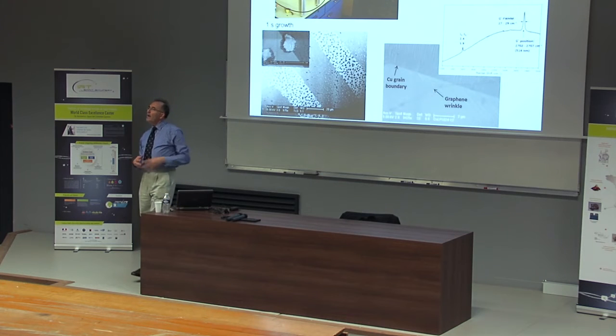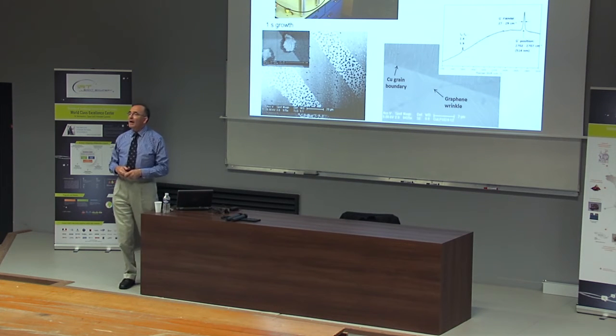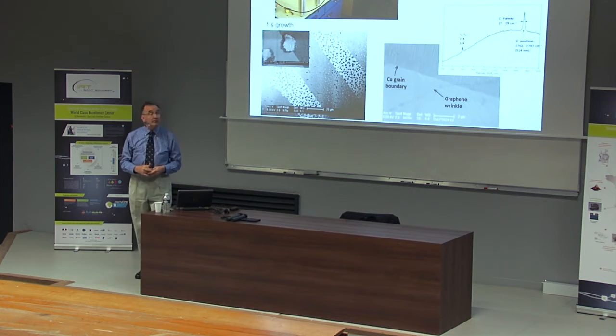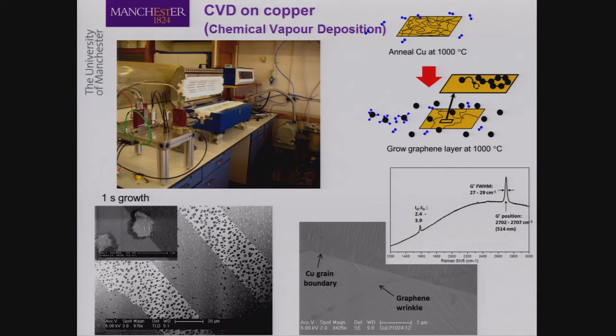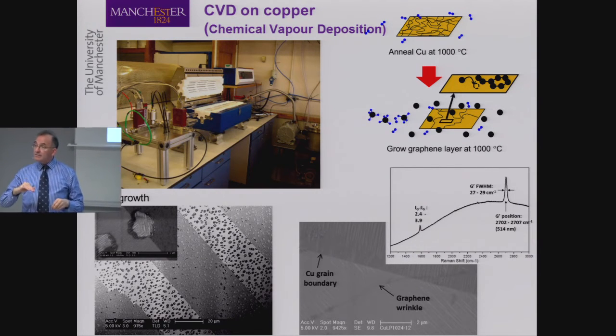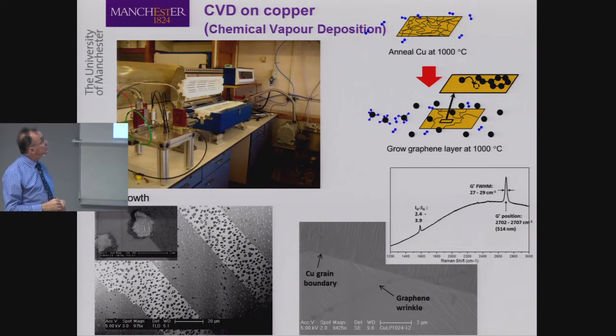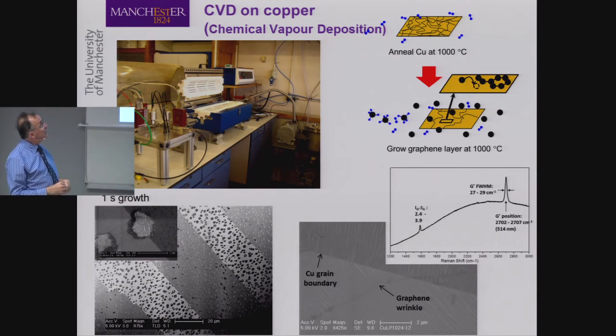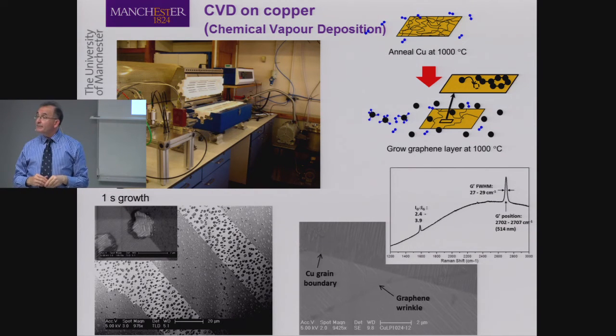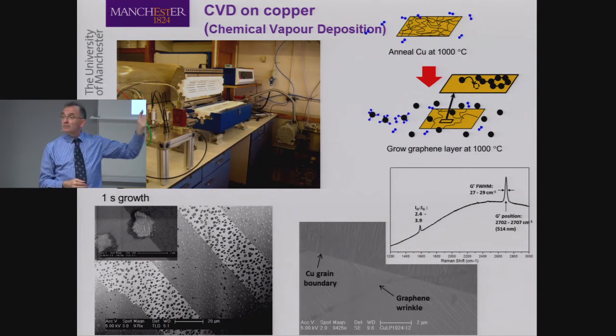Another way of producing graphene is by chemical vapor deposition. And we can see there, atom by atom, we create the layers of graphene. So you grow graphene on your copper substrate at elevated temperatures of about 1,000 degrees Celsius. Again, there is an IP behind this, because it's not as simplified as it appears on the screen.